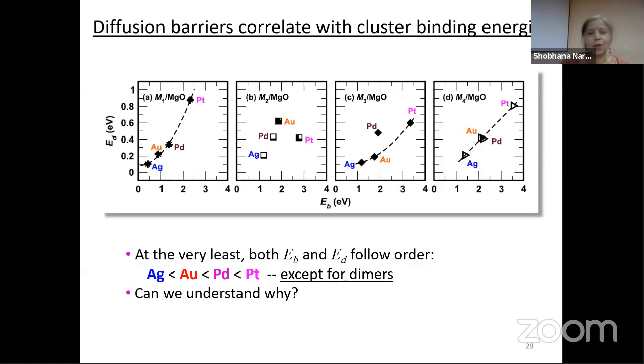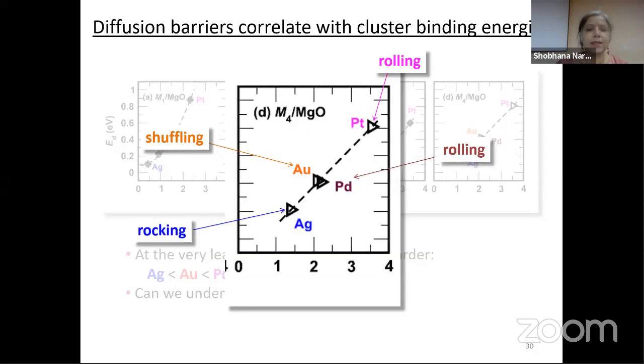Okay? So let's look at it step by step. The first thing is that the diffusion barrier correlates with the binding energy of the cluster to the substrate. You see this correlation very clearly for the monomer. You see it for the trimer, except maybe palladium goes a little bit off. And for the tetramer, it's an excellent correlation. And certainly it seems to be true that the silver comes first, then gold, then palladium and platinum, except for the dimers. So can we understand why? It turns out there's a very simple explanation for this. And incidentally, it's really surprising, okay?